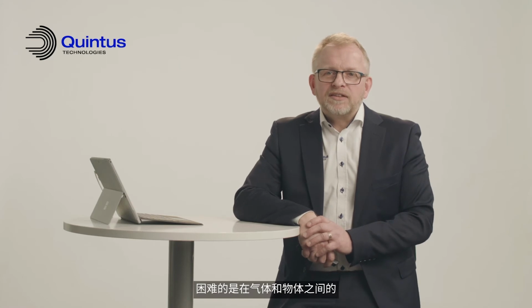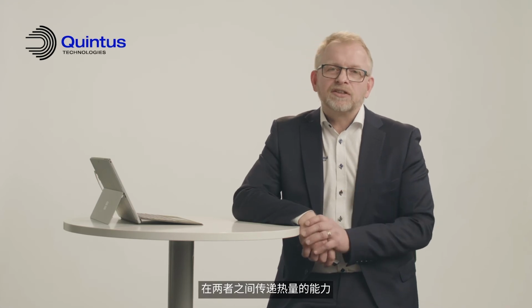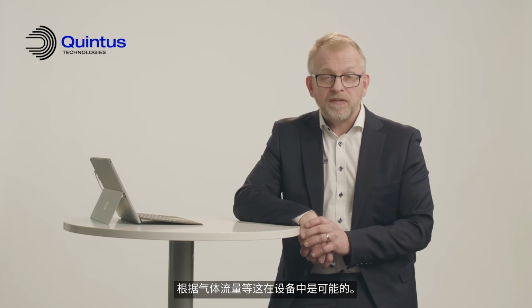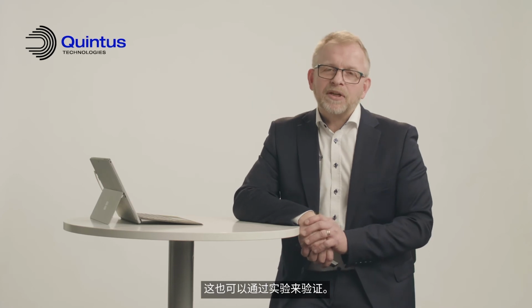The thing that's difficult to work out is the heat transfer coefficient, which is between the gas and the object, the ability to transfer heat between the two. And this can be used, if we had this, of course, to calculate the cooling power that's possible in the equipment based on the gas flow, etc. So cooling rate is basically dependent on gas flow in the equipment, if it's turbulent or laminar, the gas properties, the density, the viscosity, etc., and also the heat transfer coefficient, which can be calculated and also be checked with experimental work. So I'm going to show you some slides regarding what we've done on this.